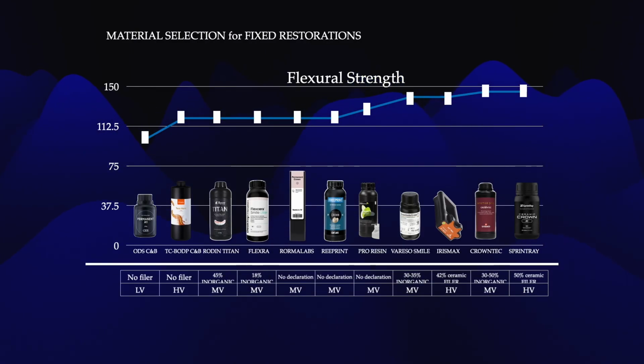If we see the result of flexure strength of the most common resins we use for permanent restoration, it is about 150 megapascal, which is very nice, and far above the enamel itself, and far above the porcelain layer in PFM restorations. Of course, PFM itself as a metal has a higher flexure strength, but the veneering ceramic layer is less than 100 megapascal. So you give our patient a monolithic material with flexure strength of about 150 megapascal.